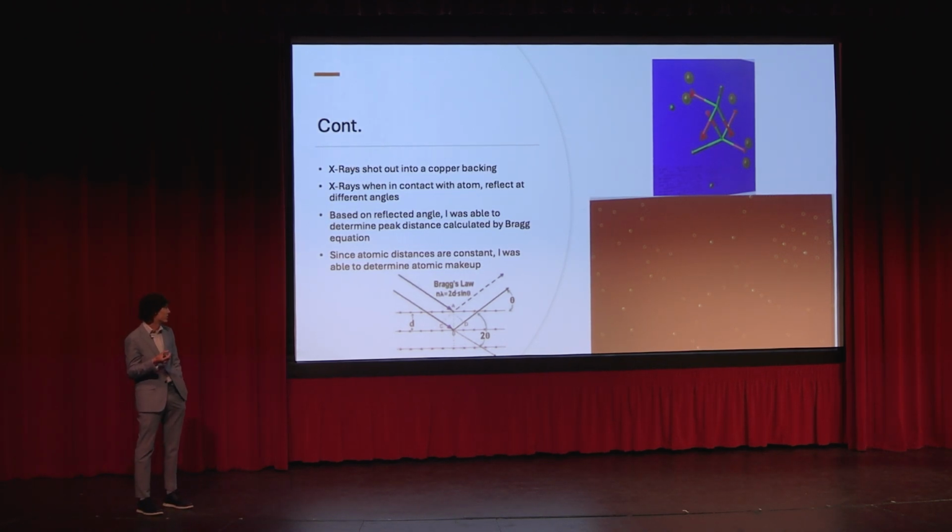So using Bragg's law again, which relates X-ray wavelength to atomic position, we can tell how far the light scattered, where atoms are going to be, and then we can use that to eventually solve its crystal structure. At the top right, this is our raw data once we translated what we got on this film into a program called OLEX2 software. And this is what the initial crystal structure looks like before we standardize it.